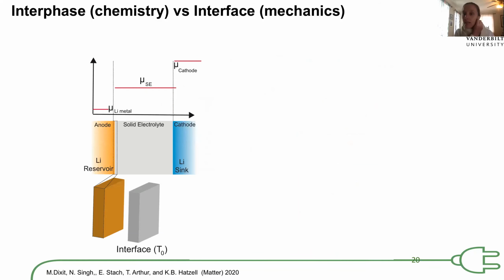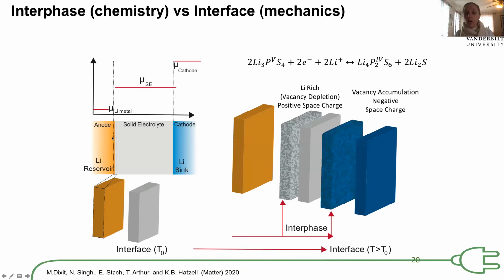Something that's interesting about these sulfides is that while they have great transport properties, they are not chemically stable with lithium metal. Again, as I mentioned previously, the chemical potential is dissimilar, and so you can form interphase regions, which have dissimilar properties from the anode and the solid electrolyte. If this interphase grows uncontrollably, you're going to have high overpotentials, as well as potentially consumptive side effects. These interphases are not all bad, though, if they are kinetically metastable and don't grow uncontrollably. There's a lot of interest in understanding the transport properties of these interfaces, as well as how they impact the chemo-mechanical properties of both the solid electrolyte and the lithium metal.